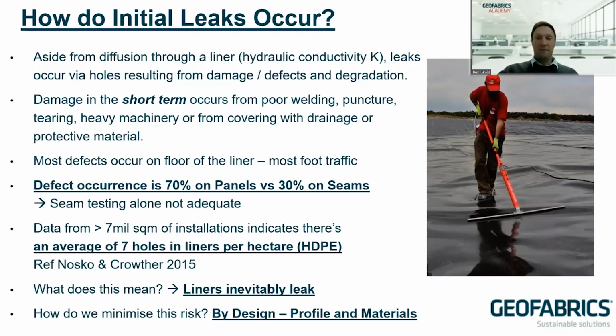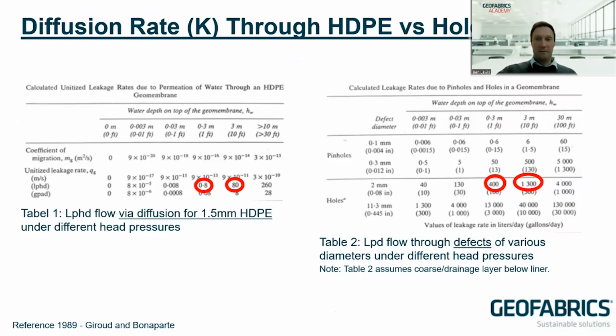How do we minimize the risk? It's by design. And just a quick stat here. The chart on the left is for diffusion rate, hydraulic conductivity through a membrane, a 1.5mm HDPE, and on the right is a leakage rate through defects. So on the left, 3 meter hydraulic head pressure over a 1.5mm HDPE, you'd expect about 80 litres per hectare per day through that membrane without any defects. Rather, through a 3 meter head pressure over a 2mm hole over a sort of porous subgrade, you'd expect 1,300 litres per day through that hole. So you can see it's the defects that really cause the bulk of the leaks, essentially.